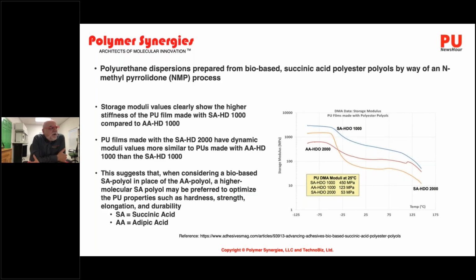Here's an example of some polyurethane dispersions prepared with bio-based succinic acid polyester polyols by way of the N-methylpyrrolidone process. The reference is given down here for Adhesives magazine. You can see that storage modulus values differ when you're using succinic acid versus typical adipic acid polyols. And we can compare the molecular weights of these. The succinic acid 1000 has very high modulus. We can see that the rubbery plateau is much higher. And we can see that the thermoplastic drop is much higher than it is for these adipic acid materials. And the 2000 molecular weight is somewhere in between here.